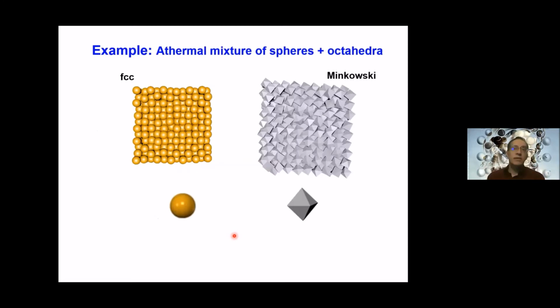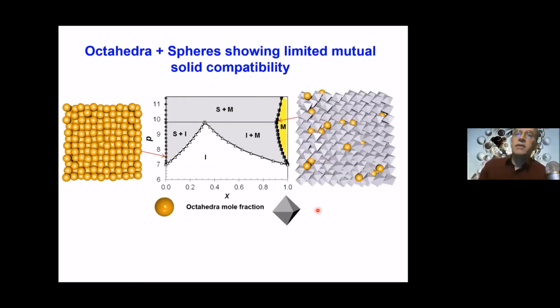I'm going to show you just one example for an athermal mixture of spheres and octahedra. So these are different shapes. They crystallize into different lattices, FCC for spheres, this Minkowski crystal for octahedra. So let's see if they are able to mix. This is an example of a phase diagram showing the osmotic pressure as a function of the composition, the mole fraction of octahedra. And this shows that this is a type of diagram known as a eutectic diagram. All the regions in gray are basically depicting the two-phase regions where things phase separate, so there's no solution there. This is the isotropic phase over here.